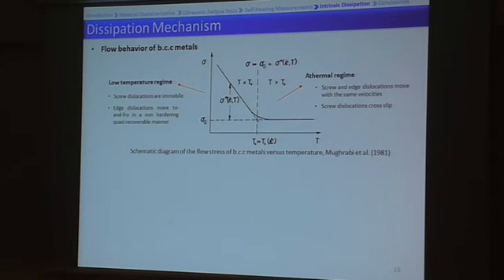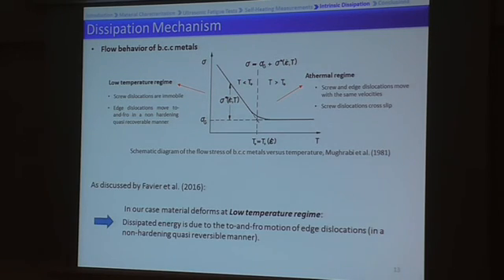So in this regime we have high amounts of dislocation motions, and the plastic strain can be localized in slip bands also. So based on our experimental observations and also based on the recent results of Favier and her co-workers for alpha iron, we concluded that in our case the material deforms at low temperature regime. So the dissipation comes from the to and fro motions of edge dislocations in a non-hardening quasi-reversible manner.